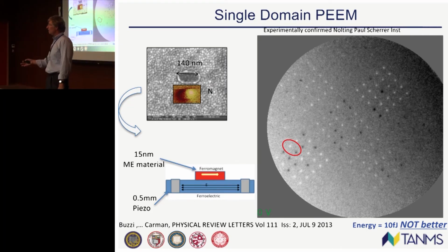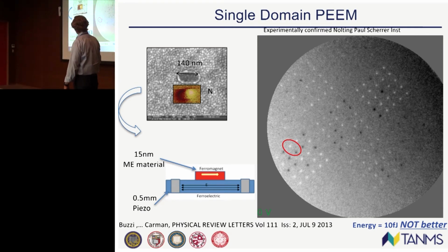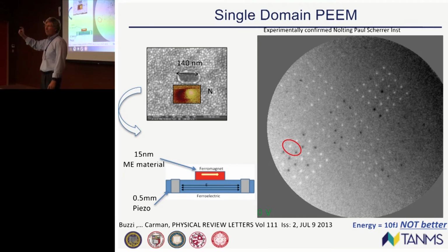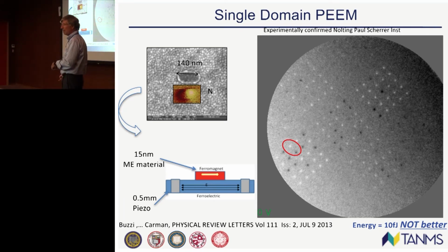You may go, well, Greg, you lied to us because this was supposed to be 1 attojoule, right? Well, I really didn't lie to you. There was a problem here. If you look at the structure that we tested, the piezoelectric substrate was 0.5 millimeter thick. The nickel nanodot was only about 30 nanometers thick. So what we did wrong was we chose a thick PMN-PT sample. Don't do that. Choose thin film.